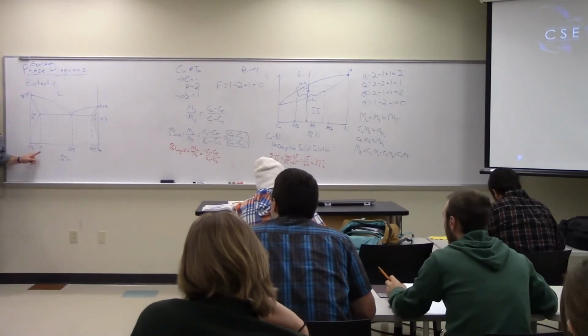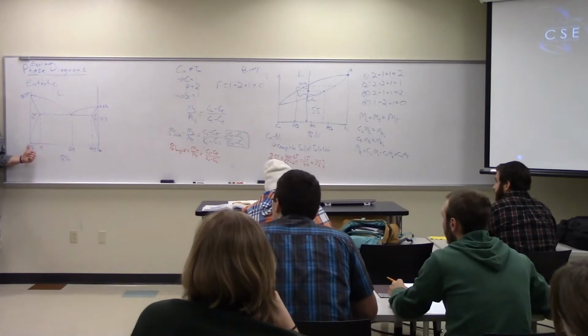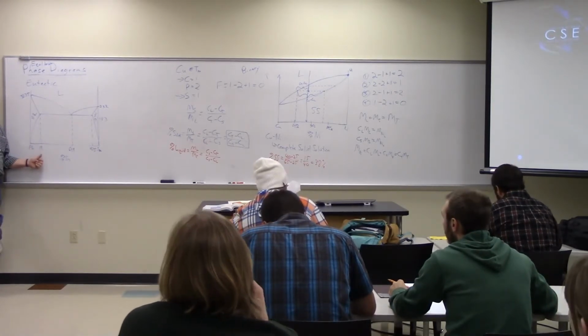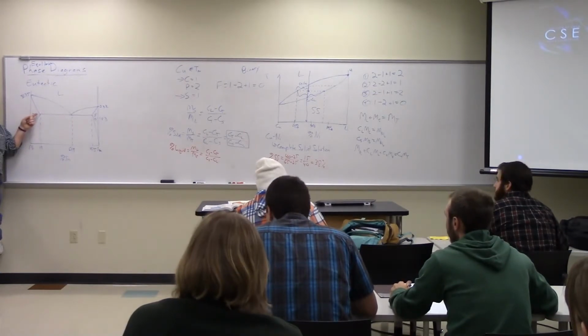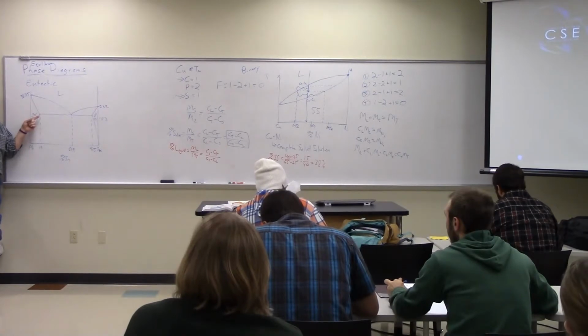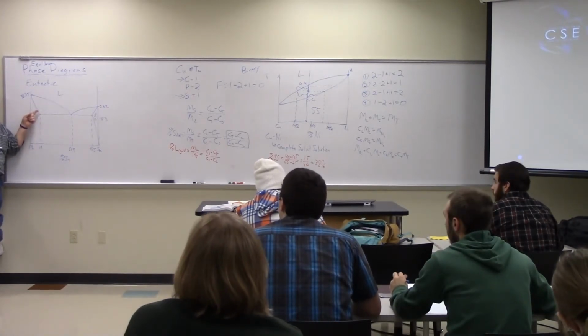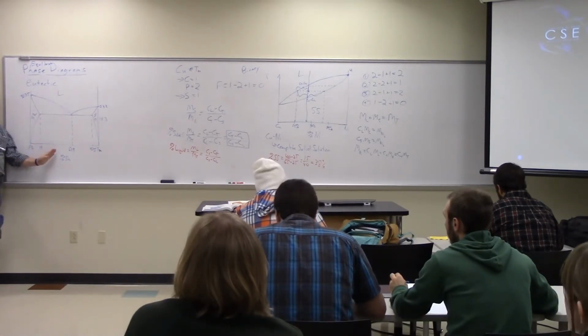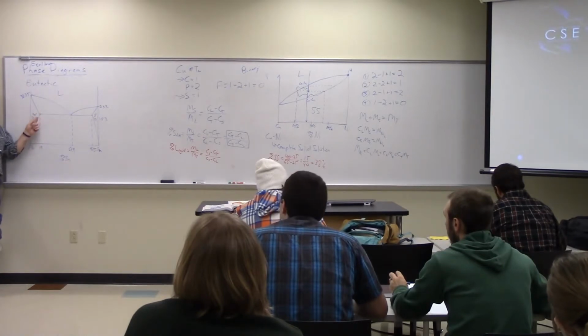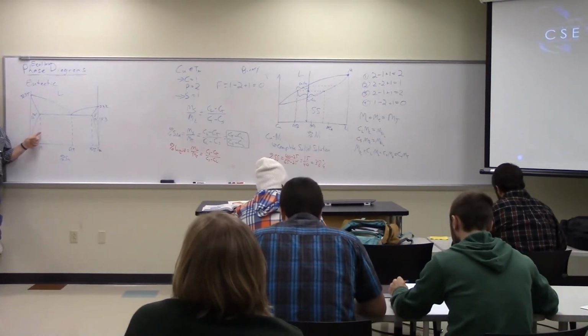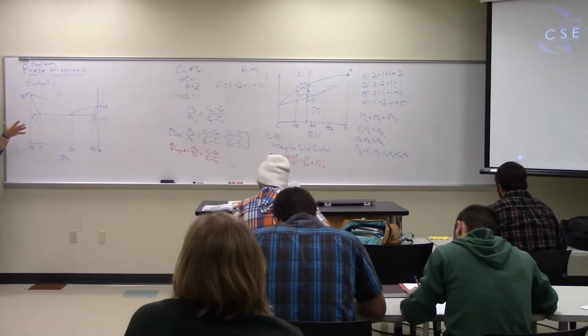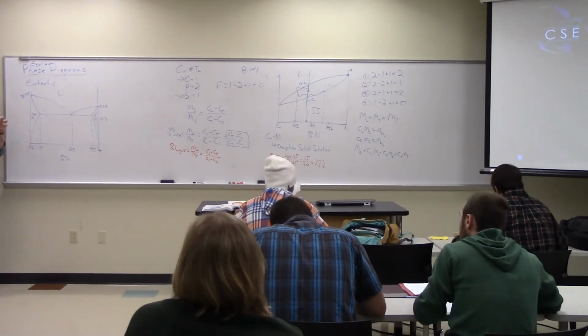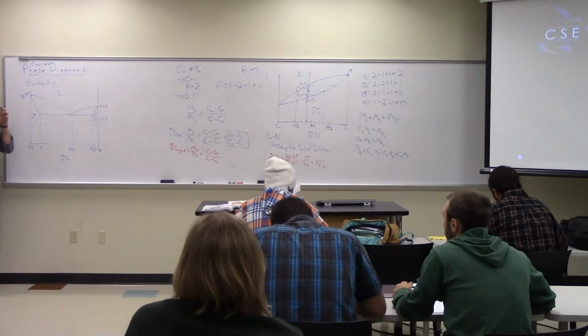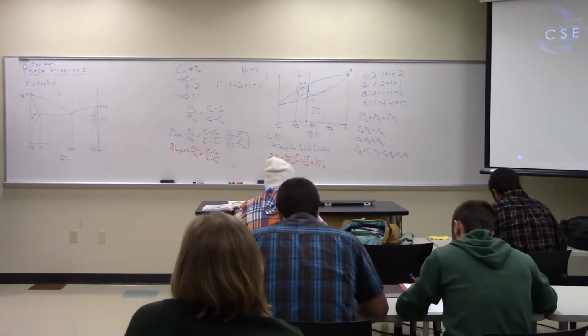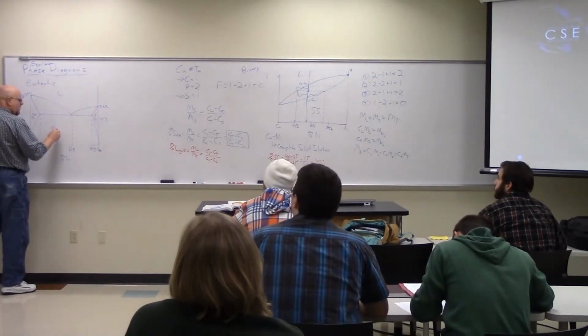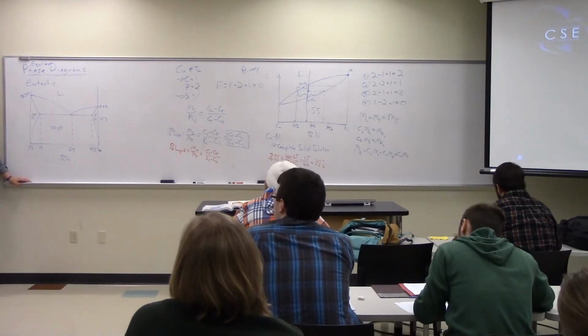In other words, the most tin that I can absorb into lead is 19%, and it has to be at 183 degrees C in order to get the 19% in. If I try to put in more than 19% tin, or 19% at a lower or higher temperature, particularly a lower temperature, that tin will not evenly distribute itself within the lead. Instead, the tin will agglomerate into chunks that are separate from the lead. So here I have a mixture of A and B, or alpha and beta. I have two different solids in this region.